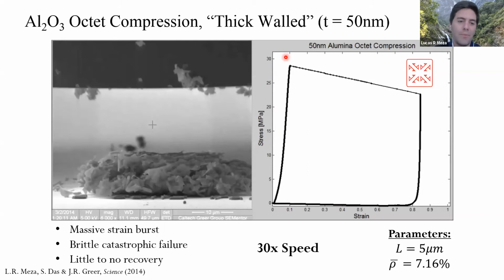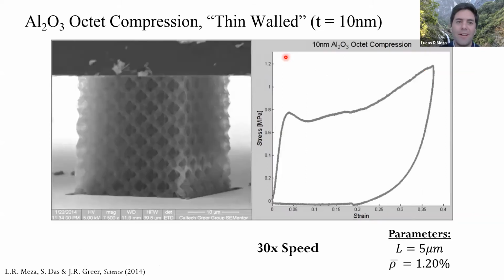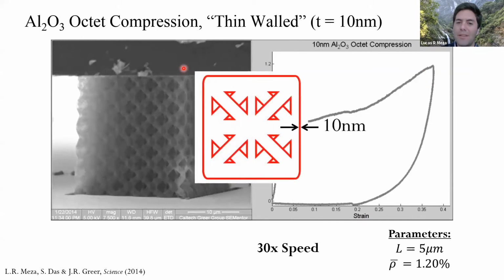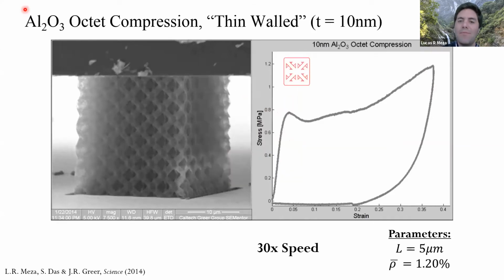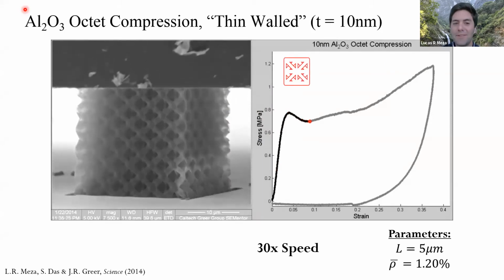Here we had taken that same Alumina octet, used the same architecture, the same material, the same geometry, the same everything, but now reduced it to be thin-walled. So this is 10 nanometers instead of 50 nanometers. We kind of came upon this serendipitously. What we found in playing around in this parameter space was quite a different behavior.